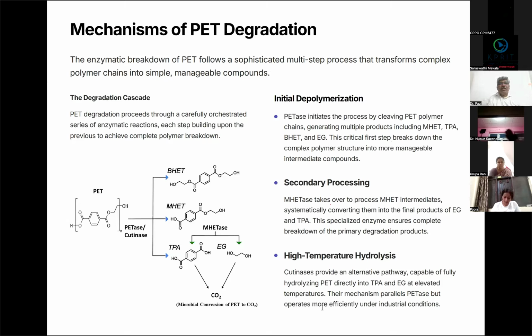The enzymatic breakdown of PET is a very sophisticated process, and it involves three steps: initial depolymerization, secondary processing, and high temperature hydrolysis. The PETase initiates the process by cleaving the PET polymer chains, generating multiple products including MHET, TPA, bis-hydroxyethyl terephthalic acid, and ethylene glycol. The secondary processing involves the MHETase, which takes over the MHET intermediates, systematically converting them to the final products, ethylene glycol and terephthalic acid.